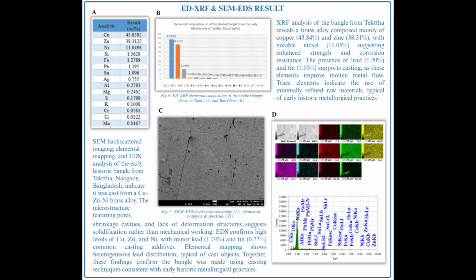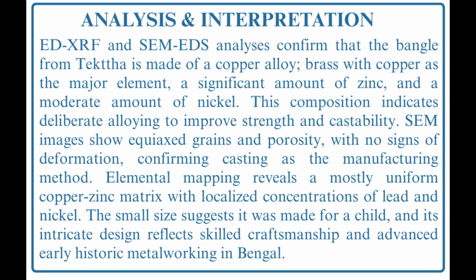SEM imaging showed equiaxed grains and a uniform metallic matrix, which are strong indicators of casting as opposed to hammering. There were no signs of deformation, supporting the conclusion that this object was manufactured using a controlled casting process. The combination of XRF and SEM-EDS results strongly indicates that the bangle was made using a copper-zinc-nickel base alloy with deliberate additions of other elements to improve durability and casting performance.